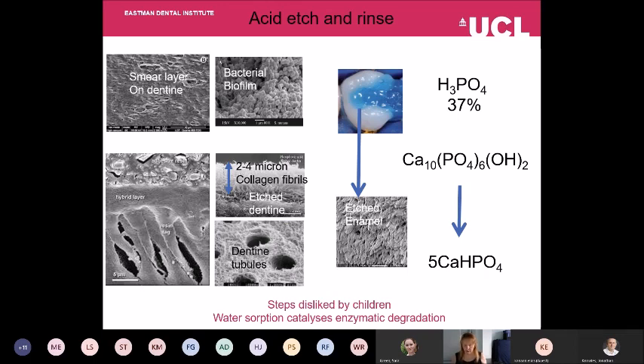What you also do, though, is you etch the dentine structure. What this gives you on the top surface of the dentine is a layer of around 2 to 4 microns thick, which is made up of collagen fibrils that are demineralised on top of the sound dentine. What it also does is it opens up the tubules, the dentine tubules. Getting bonding to this is much more difficult than to the enamel because these tubules contain water and they repel the hydrophobic composite.